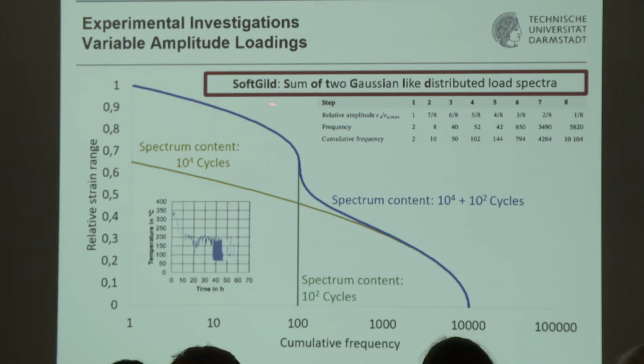This spectrum consists of roughly 100 cycles with a large amplitude. The amplitudes are normalized here, and this is the largest one. There are roughly 100 smaller cycles with smaller amplitudes per large cycle. So the spectrum looks like that. It is something more or less in between a straight line distribution and a parabolic distribution, which I have shown in my first figure, and the number of cycles in each step you can take from this table.